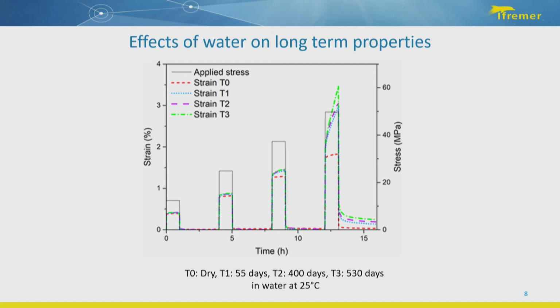Again, this is not easy to describe without a pointer. What we've done is we've done creep recovery tests on an epoxy material. We did them first dry. So those are the square blocks, or the rectangular blocks, showing the stress. So we increase the stress for an hour and then unload for 3 hours. And then the colored lines are tests which were done after aging to different degrees of water ingress.